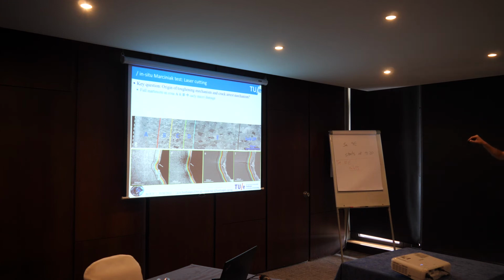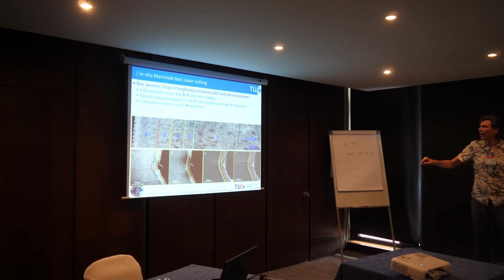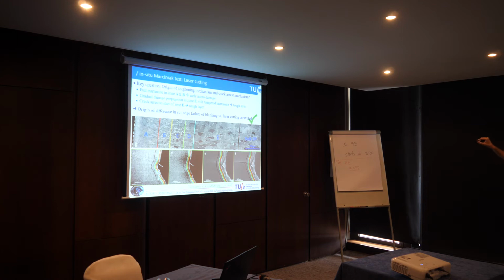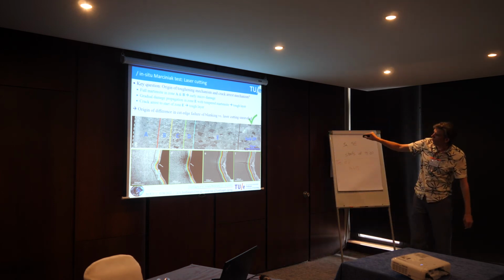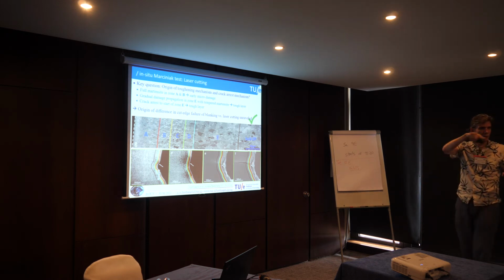That's a tempered martensite. So the full martensite, that's really region A and B, early micro crack. And then we just have a very gradual damage propagation into zone E with the tempered martensite, and that's really the tough layer. And there it really gets stuck for some time, a crack arrest. And that really explains why there's such a big difference. In comparison with the bulk material, the tough layer helps a lot. So we created basically this protective layer by doing laser cutting.